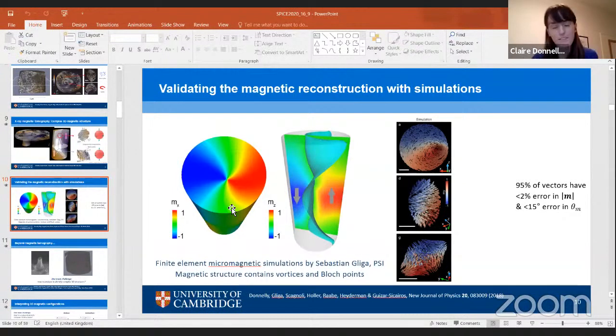To go into a little bit more detail on what the algorithm is, it's a gradient-based iterative reconstruction algorithm. We don't assume any particular magnetic structure. We actually start with an initial guess, which is zero. So this really means that we have a surprisingly accurate reconstruction based on these XMCD projections.